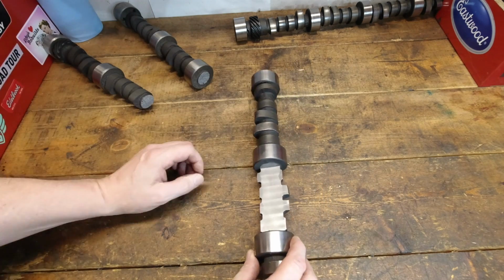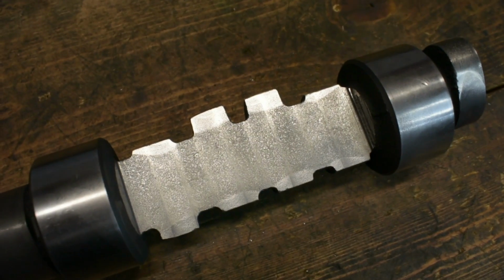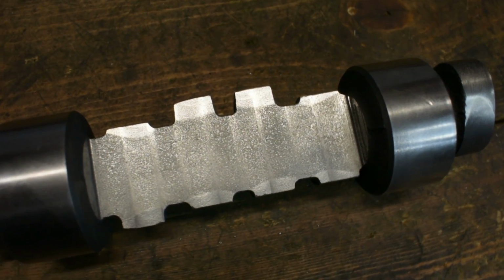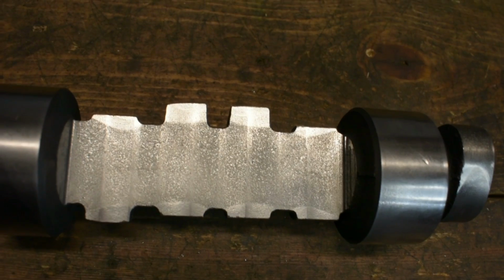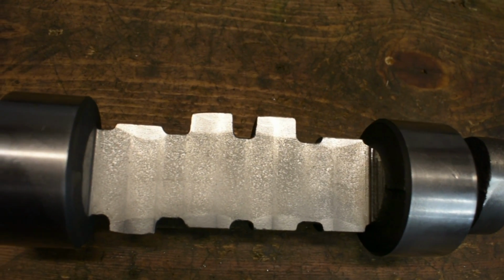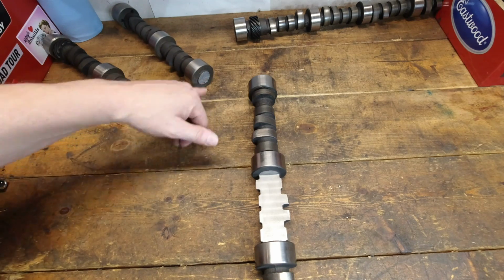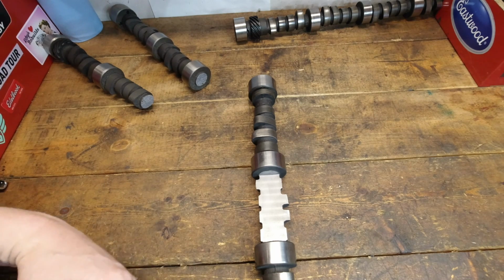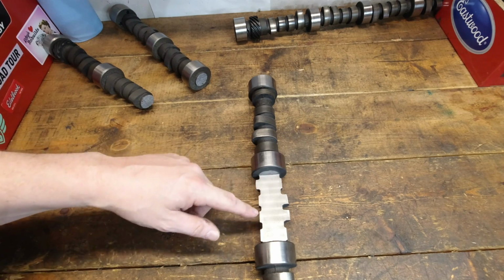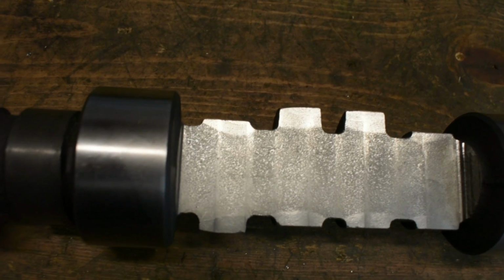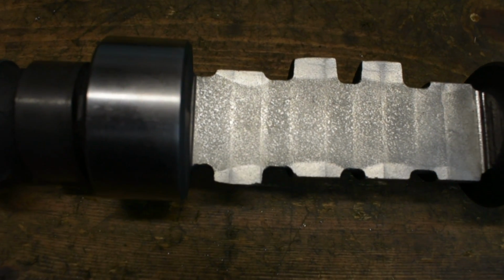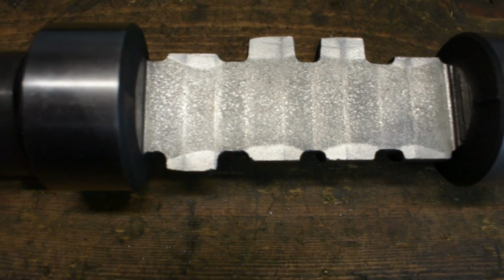So we take a look at this cam that I had cut down. You can see fairly effectively where those lines are on the material and how deep that heat treating goes. If you look here, it's snapped right off at the journal, but you look and see the lines here, you can see just how deep that heat treating goes. And on a cast cam core, they do go fairly deep.